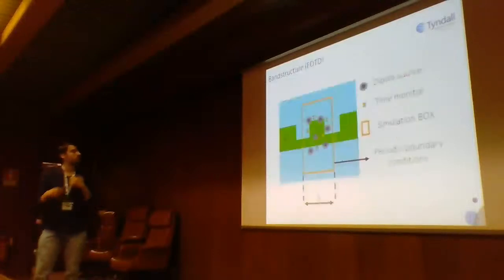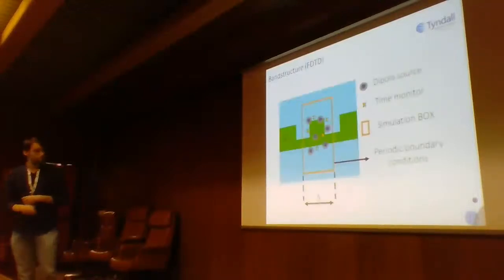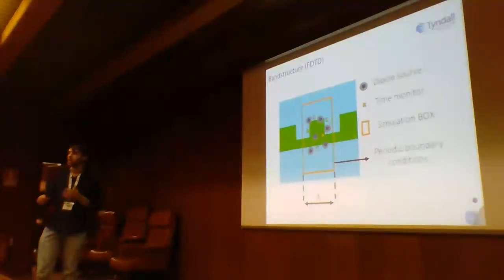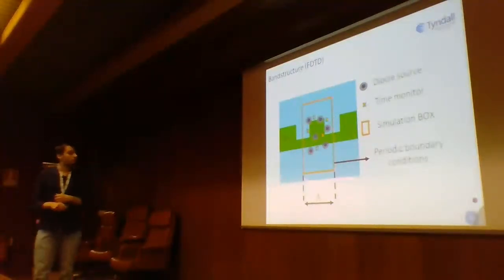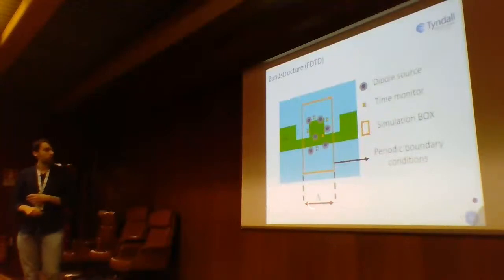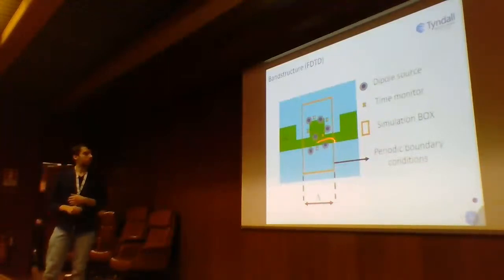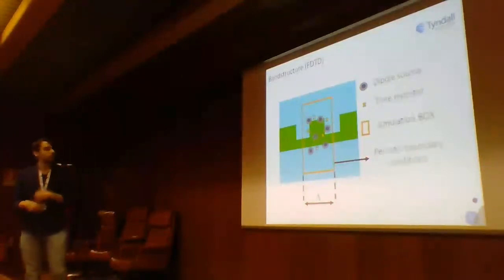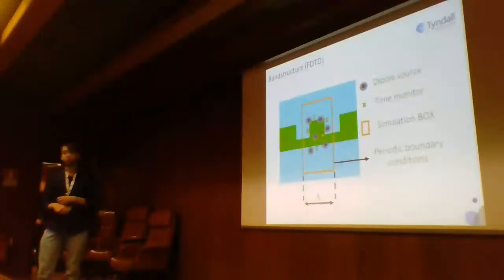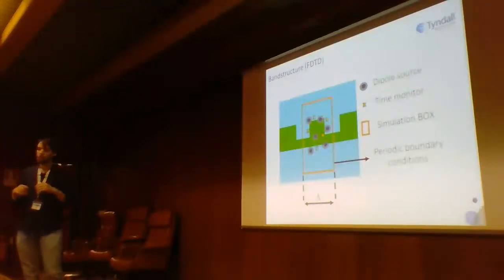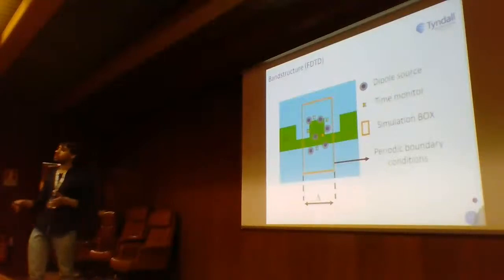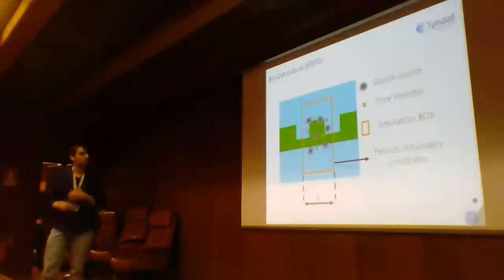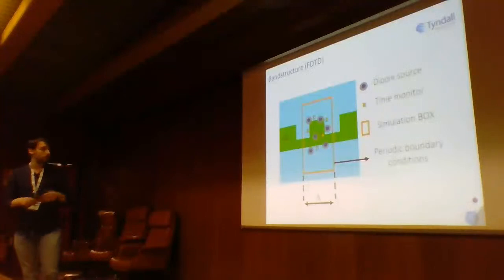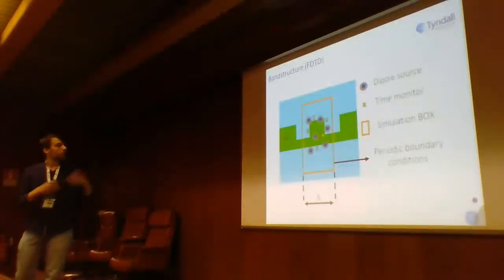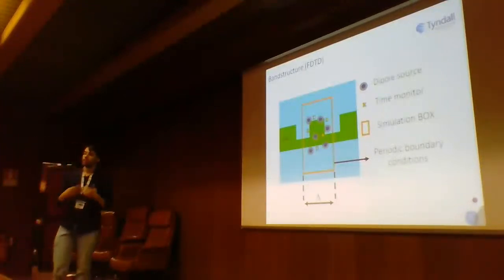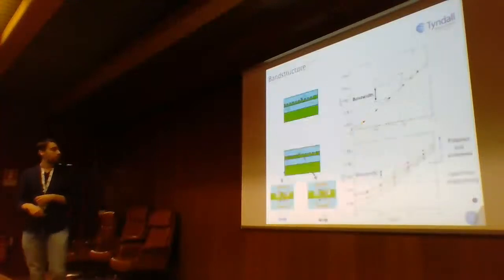So first of all, what we can use is, again, the FDTD method. We can recreate our structure inside the simulation software, and we define our simulation box that has a width of the pitch of the structure, and setting a periodic boundary condition, we can use a dipole source to excite all the modes of our structure. And using the time monitor, what we can get is basically the time response in terms of the electromagnetic field. And then doing the Fourier transform, we know the modes that are sustained by our structure.